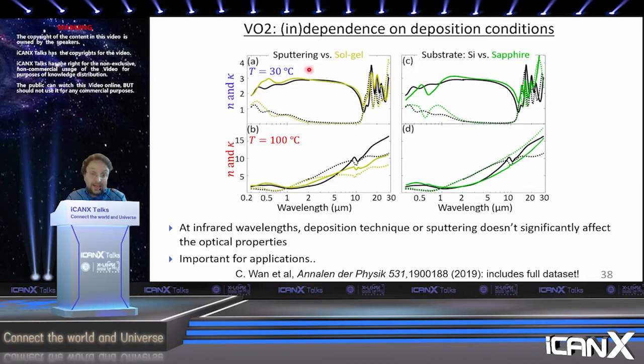And so what we found is that the complex refractive index of VO2 changes dramatically depending on the deposition technique, whether you sputter or do sol-gel synthesis, for example, or whether you deposit it on silicon versus sapphire, because there's an epitaxial relationship between the film and the substrate. But there is this magic range, and again, it's this 2 to 11 micron range, where the deposition conditions don't seem to matter too much, and the complex refractive index is more or less the same. Over here in the visible, for example, you have big differences, and in the far infrared, you have big differences, but in this magic 2 to 11 range, which is again away from the resonances, both on the short wavelength side and on the long wavelength side, VO2 is roughly sample independent as far as its optical properties go. And that's really important for applications.